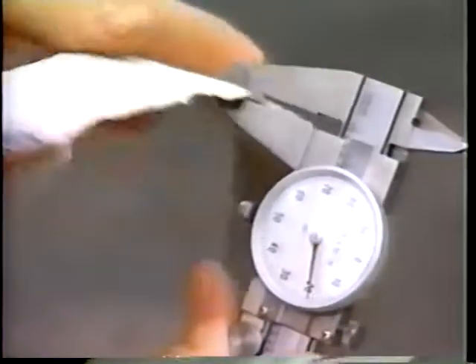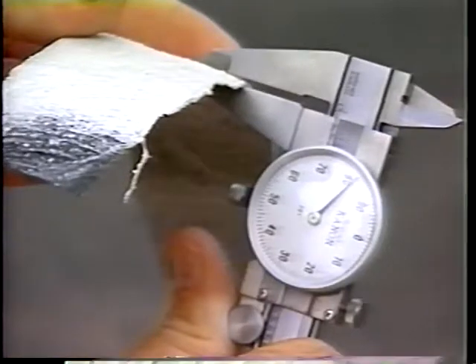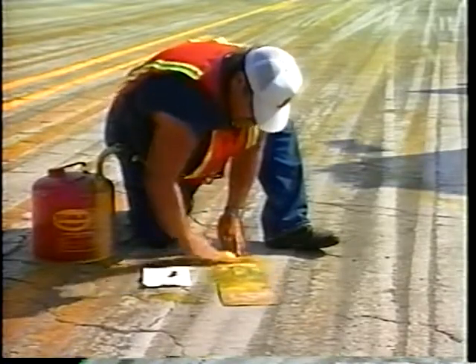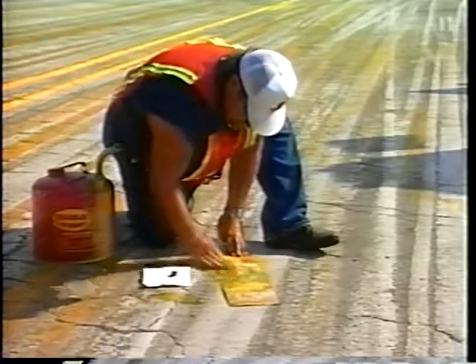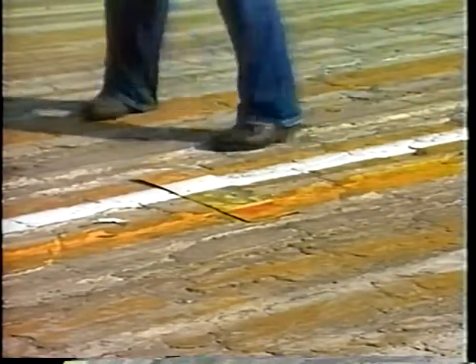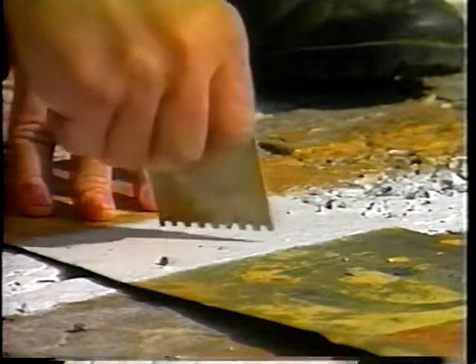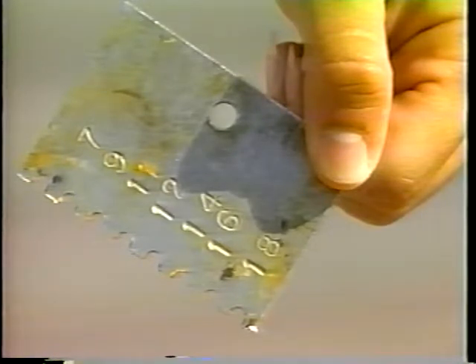Daily measurement of film thickness should be taken for project record. Thickness measurements of applied markings generally are made without drop-on beads, while the film is still wet. This is done on test plates placed in front of the striping machine moving at normal striping speed. The test should be made quickly after application using a wet film thickness gauge before the materials begin to dry.